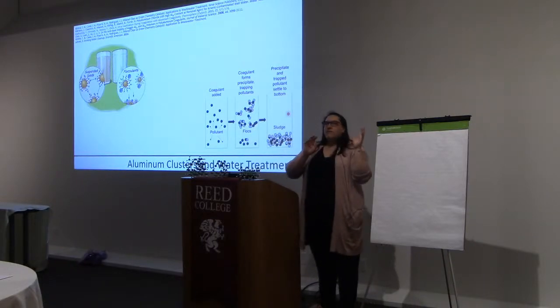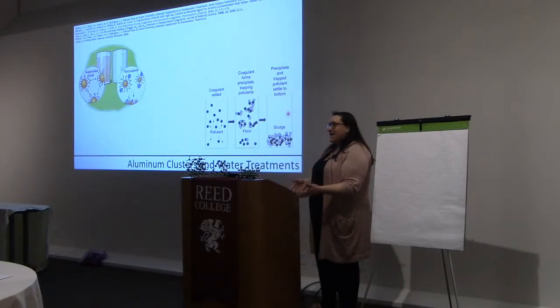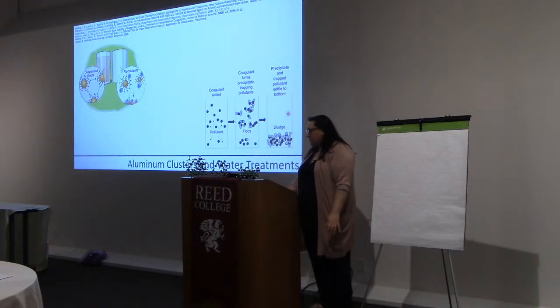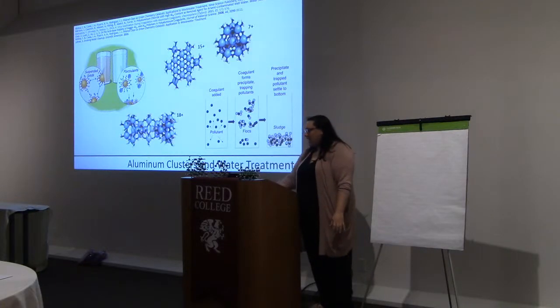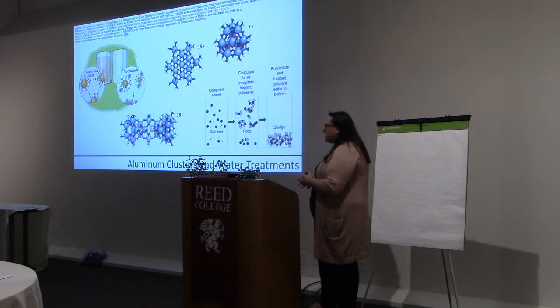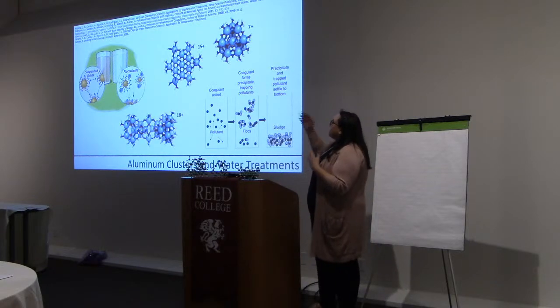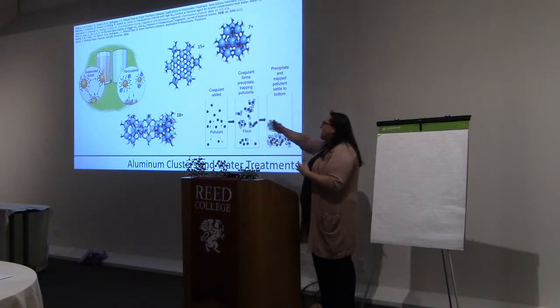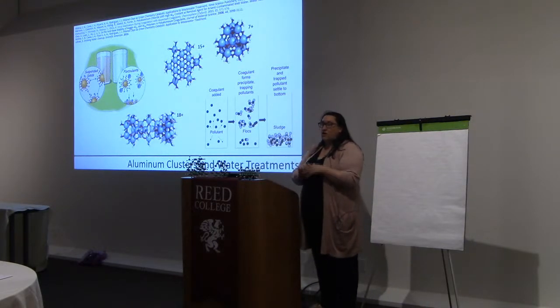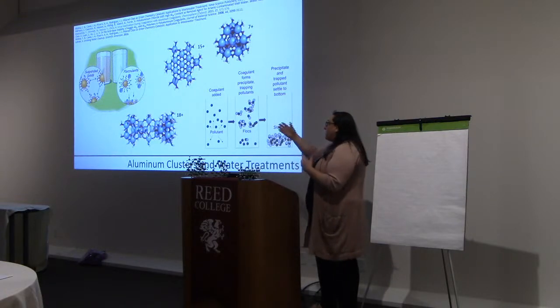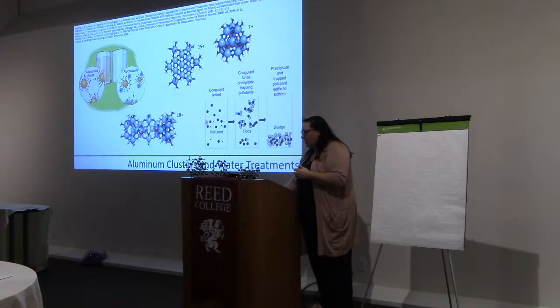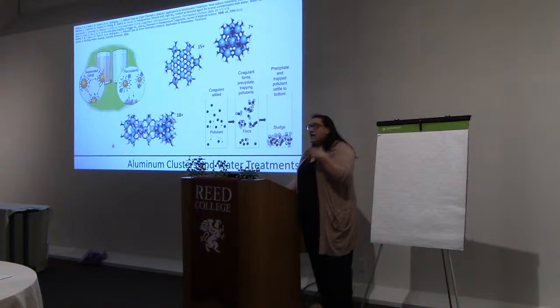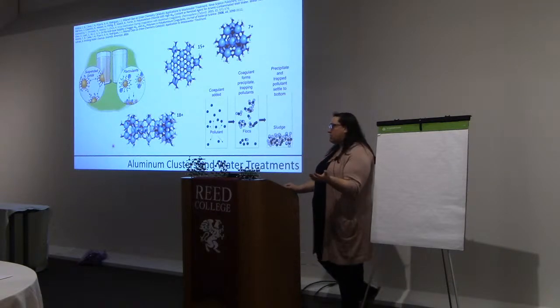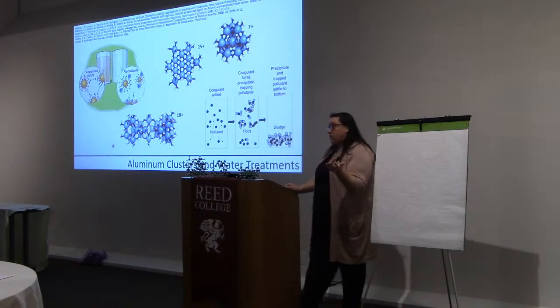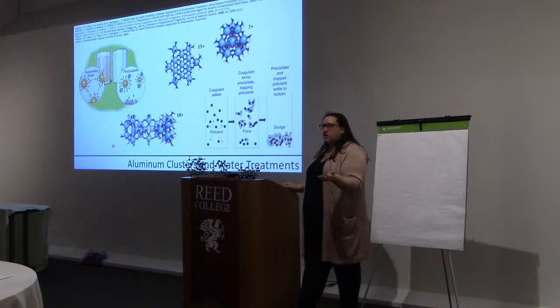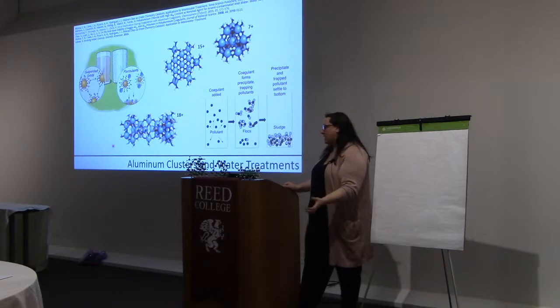When you have the monomer aluminum, it has a 3+ charge, but our polyatomic ions, our clusters, have 15+, 7+, 18+ charges on these polyatomic ions. So this aluminum 30, or this large polyatomic ion here, is a really great water treatment starting material because it already has this huge high charge, and it's going to very quickly pull a lot of things out of solution.